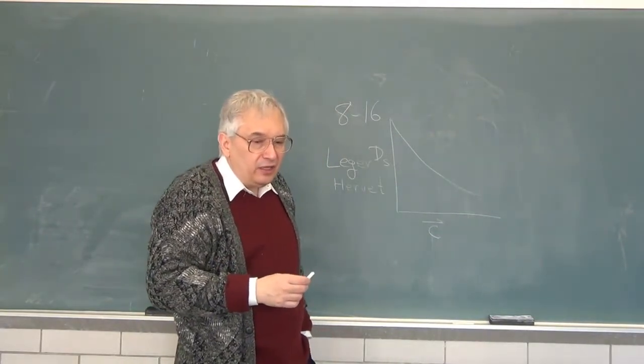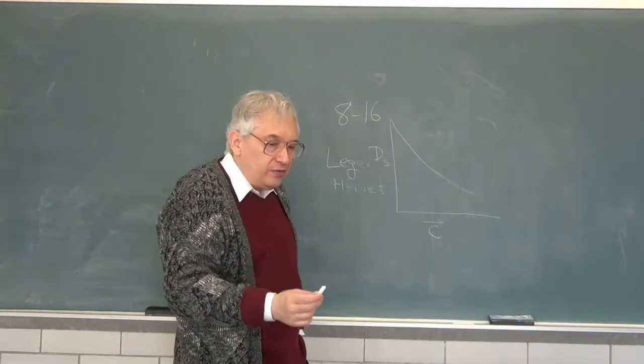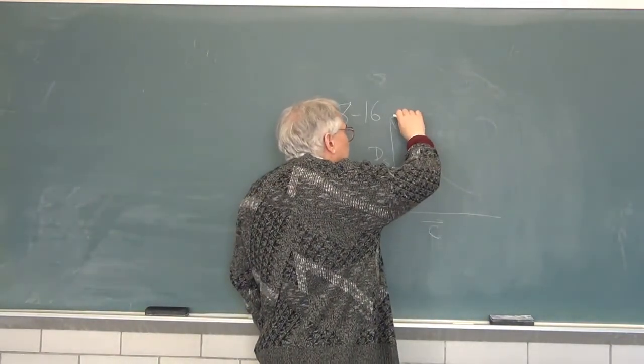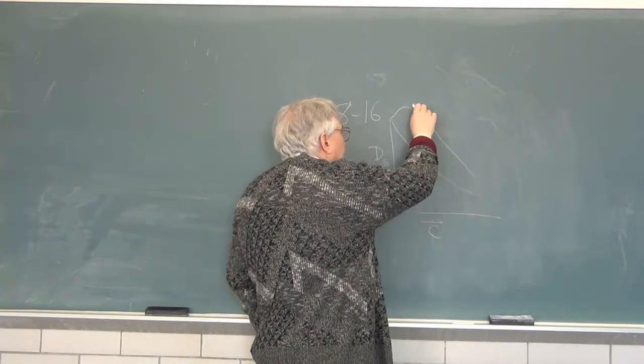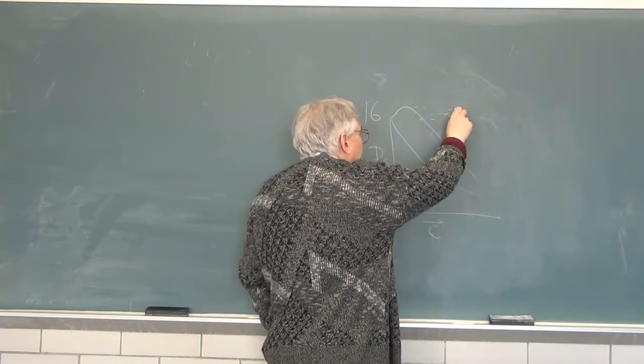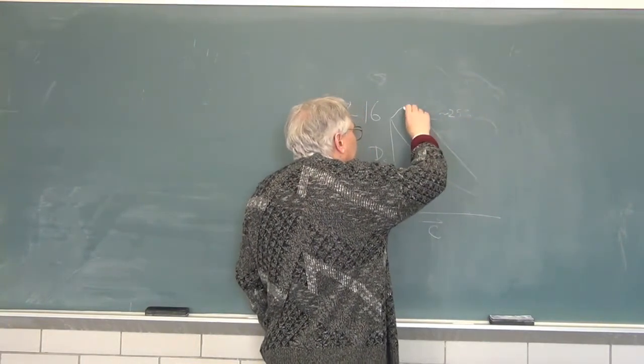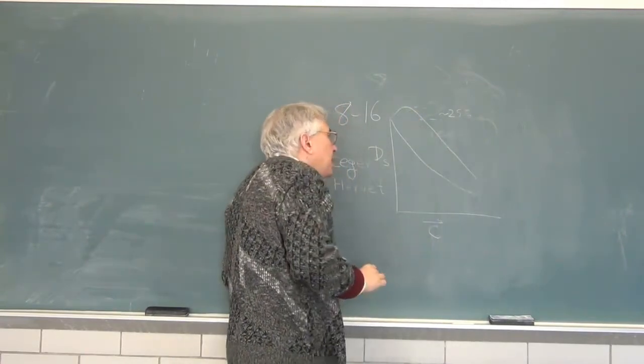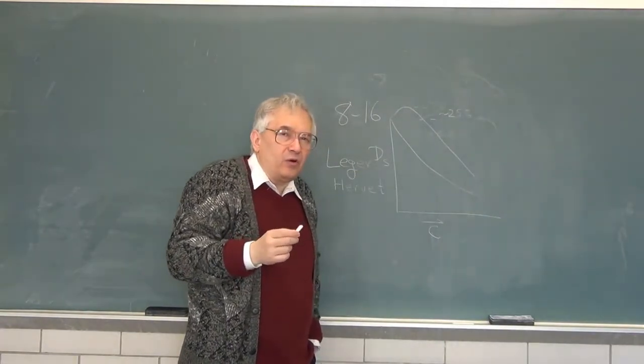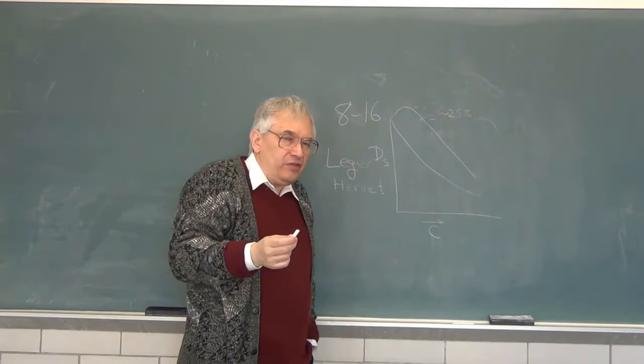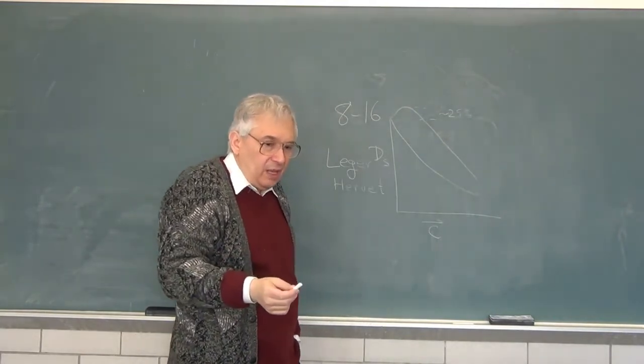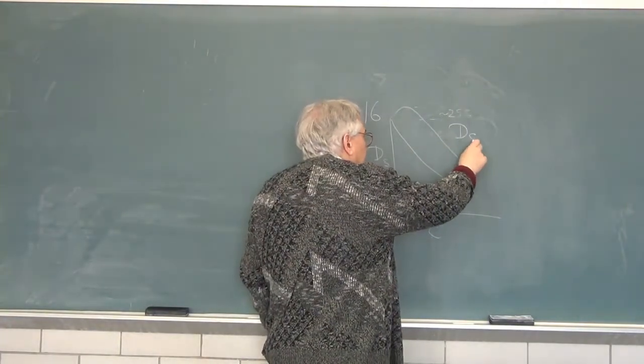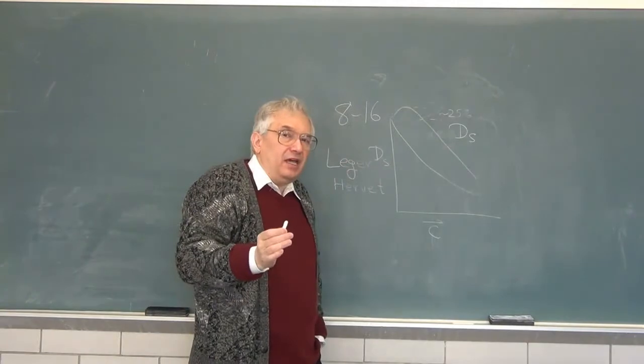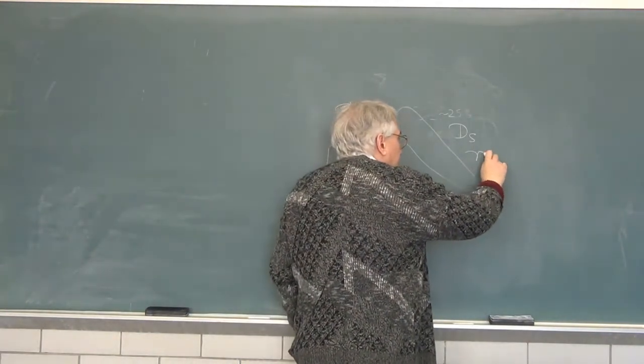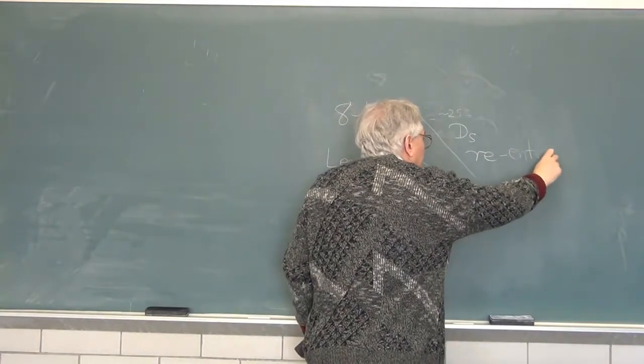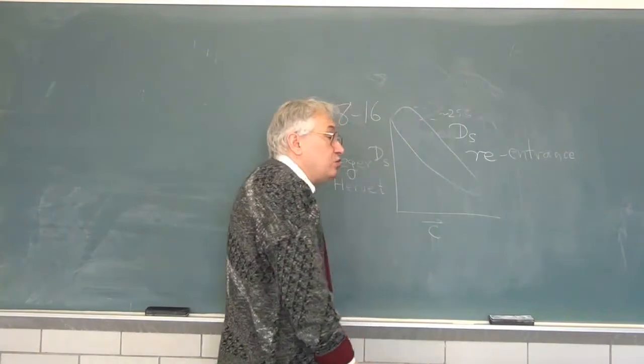You also notice a slight anomaly if you look hard at the self-diffusion measurements on the graph. Your data actually looks like that. That is, there is this hump, which is, oh, to my eye 25%, but I've heard it described as a bit larger. It depends where you measure it to. The diffusion coefficient of the probe first increases with increasing matrix concentration and then falls again. This is for D-self. The tracer measurements don't show this. Now, you could say this is an example of reentrance. Reentrance is a phenomenon we will be encountering once and again as we go through the course.